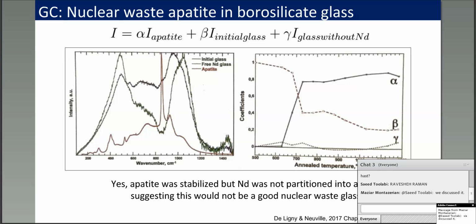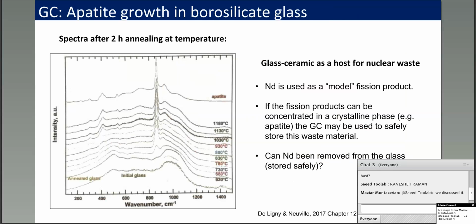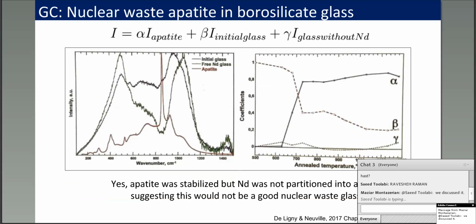Sure. And yes, when they did linear mixing, they took these spectra here and treated them at different temperatures for 2 hours and looked at the product, and you can see this gigantic peak rose out of the middle of the spectra. They did a linear combination of the spectra for apatite here in red. This is the apatite spectra with this strong peak. And then they made the initial glass here free of neodymium, sorry, here, and then the glass with neodymium. And they tried to make a mixing to reproduce the spectra of those treated samples I just showed. And what they showed is that you do form this crystalline apatite. Alpha refers to apatite. And you do have a reduction in the amount of glass, but you don't have a reduction in the glass without neodymium. So their result was not successful in removing the neodymium from the glass into the apatite phase.